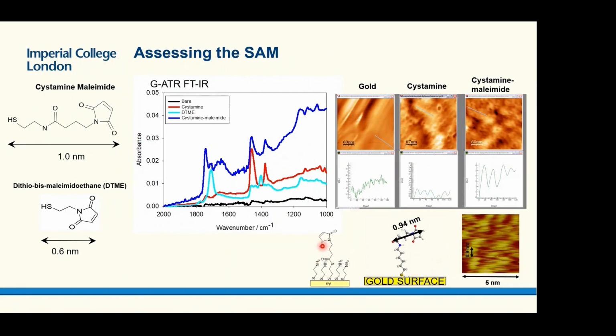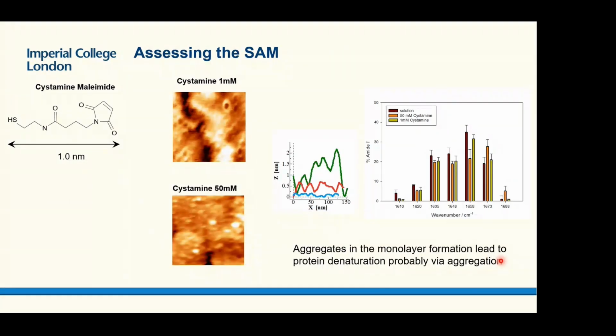You get steric hindrance, so there will be practically a carpet of cysteamine underneath, and then some maleimido groups bound in different positions. So you get a mixed surface. And you can see that also with AFM, and if you do STM, you can see that more clearly.